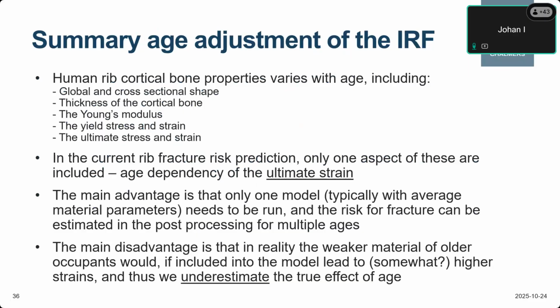The main disadvantage is that in reality, the weaker material of the older occupants would, if it were included in the model before we start the simulation, to some extent result in higher strains. And that means that we probably underestimate the true effect of age.